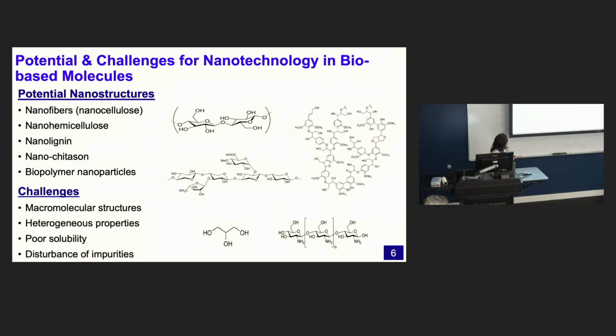So what are the challenges if we want to use nano self-assembly to make materials from these bio-based materials? If you look at the structure of these biomolecules, like cellulose, they are linear polymers, but they have a high degree of polymerization, about 15,000. So it's very hard to handle these macromolecular structures. It's not small materials. And for example, the lignin has a cross-linking structure.